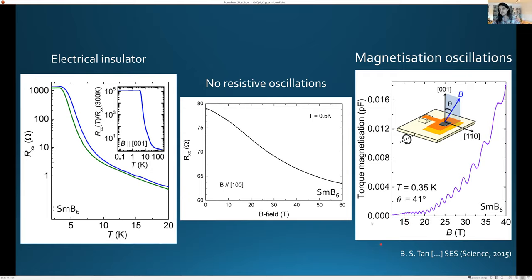If there was no sample, you would see a quadratic, or well, if there was a paramagnetic sample, let's say you'd see a quadratic in H if you had a linear M versus H. And so one sees a roughly quadratic background, but one sees hugely prominent quantum oscillations on top of it. And I'll show you in a bit, these are periodic in inverse magnetic field, which is what we would expect for Landau quantization. So yes, we are extremely confused at this point about how we're seeing such big oscillations in a material which in the bulk is clearly insulating.